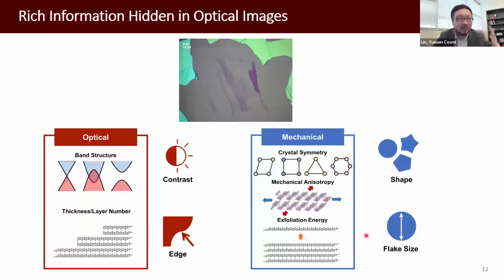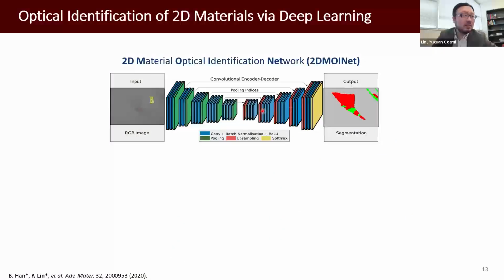If we have automated exfoliation, those processes are actually perfectly controlled. Then the shape and scattered information, the thickness, etc., are very correlated with the mechanical properties like crystal symmetry, mechanical anisotropy, and exfoliation energy. So this information is embedded in the shape and flake size, in those graphical features. So we developed this UNET-based neural network, so we can take advantage of both the optical and the mechanical properties and features.